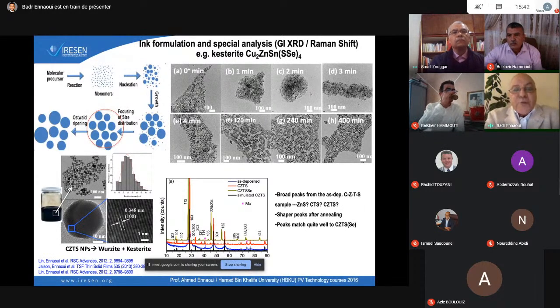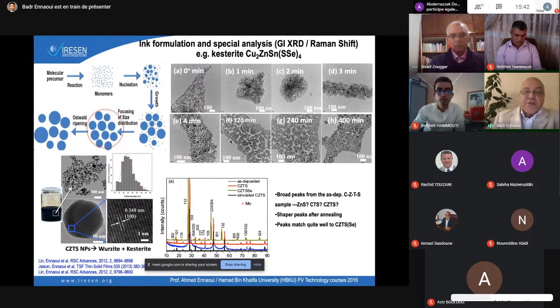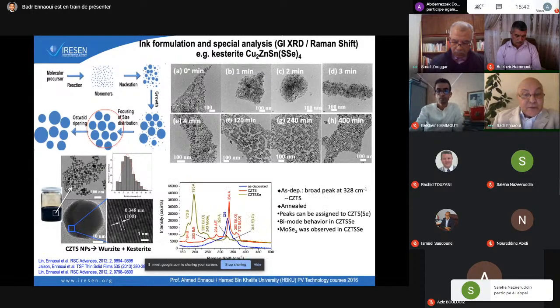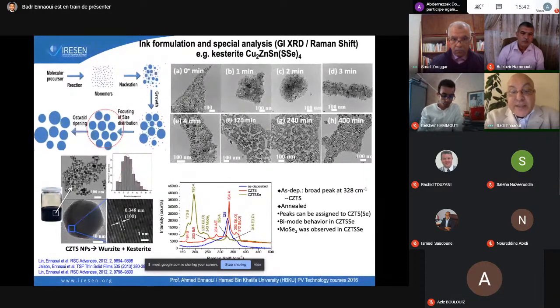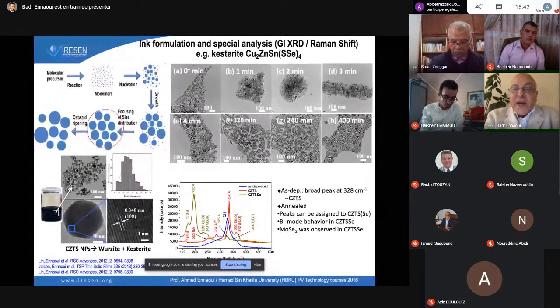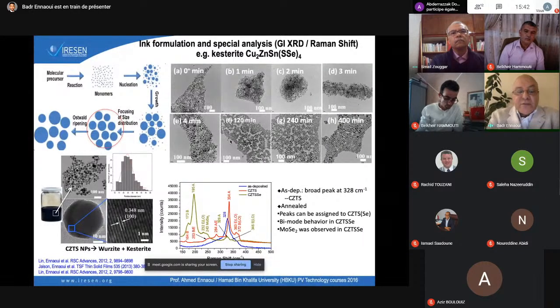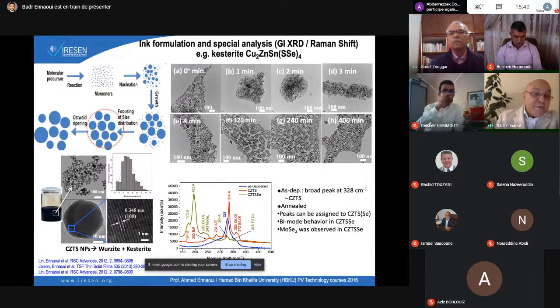And we studied this with X-ray diffraction. We studied this with Raman. These are two methods which are very important to develop at a university if you want to make nanosynthesis. X-ray diffraction is very important, and Raman spectroscopy is very important. The two methods are good enough, and if you have a high resolution scanning electron microscopy facility, then you have everything to do this kind of study. So we were able to make a very good nanoparticle and to control it and to use it as ink.